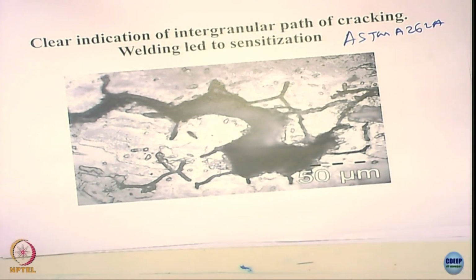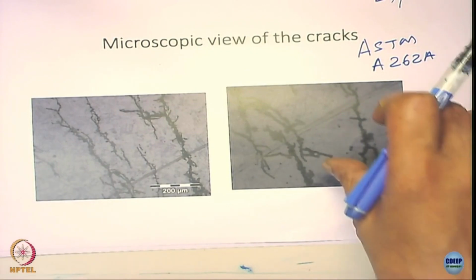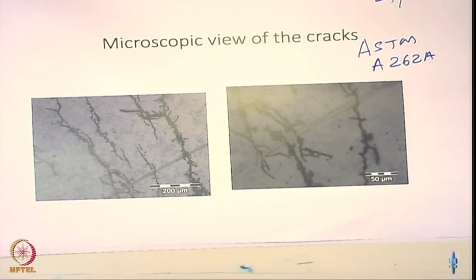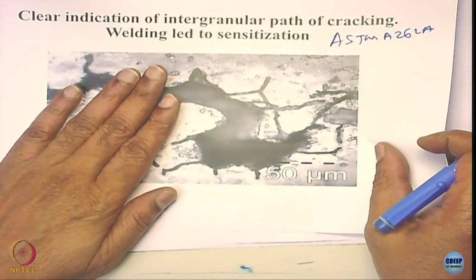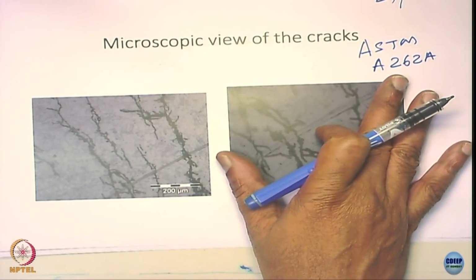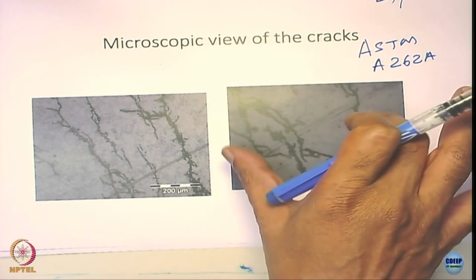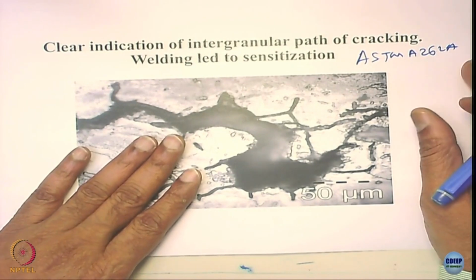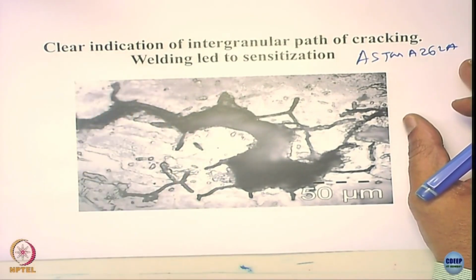So the alloy failed by brittle fracture in case 1 and case 2, but the reasons for failure are different, right? The reason for failure in this case is improper solution annealing or improper welding, or some such thing. Here everything looks okay, but the alloy is not good enough for the environment. So the way you diagnose the problem is different. In this case you say the metallurgy is not adequate for the severity of the environment, so you need to change the alloy. Here the primary cause seems to be sensitization, which is related to carbon content, welding, improper solution treatment, so many factors. So you need to understand how the cracking takes place before we can come to a conclusion about the root cause of the problem in stress corrosion cracking.